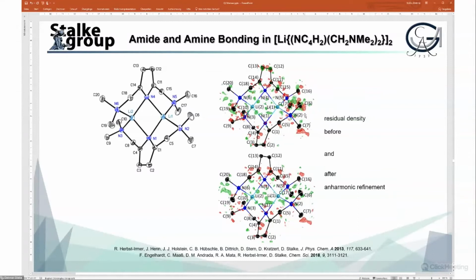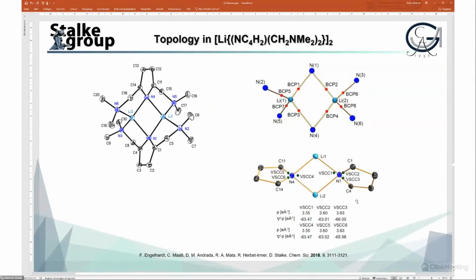And then we cured the data for anharmonicity and got an even nicer result. As you can see, C6 is now cured from that, and so is C19. With that data, we did the multipole refinement and topological analysis, so we could find all the bond critical points, and we looked at the VSCCs again. To our surprise, we could only find 3 VSCCs at every nitrogen, at the amide nitrogens.